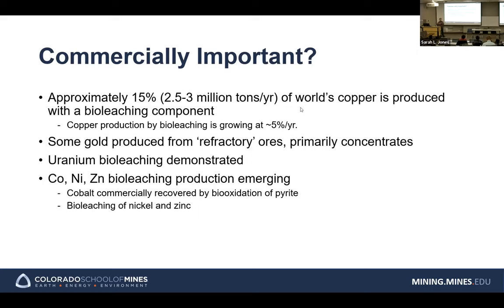So instead of putting in microorganisms, they can provide air blowing from the bottom of the heap and provide the nutrients, so they can take advantage of the bioleaching, the biooxidation process. And then there are some other operations that actually grow those microorganisms on site and add them to the heap leaching operation. And in the gold operation, some gold is produced from the refractory ore and primary concentrate.